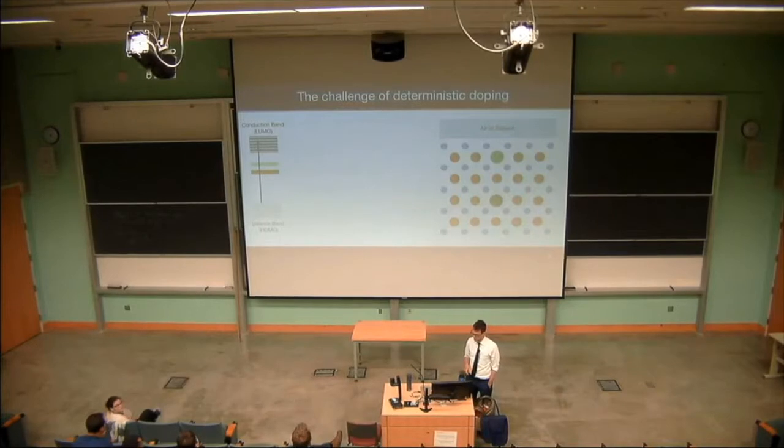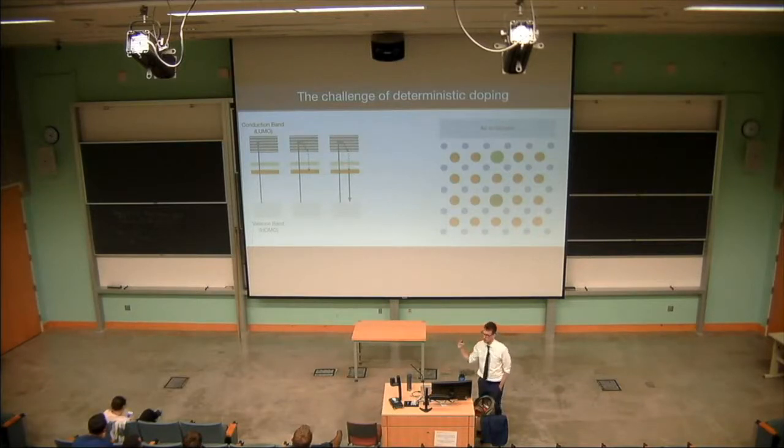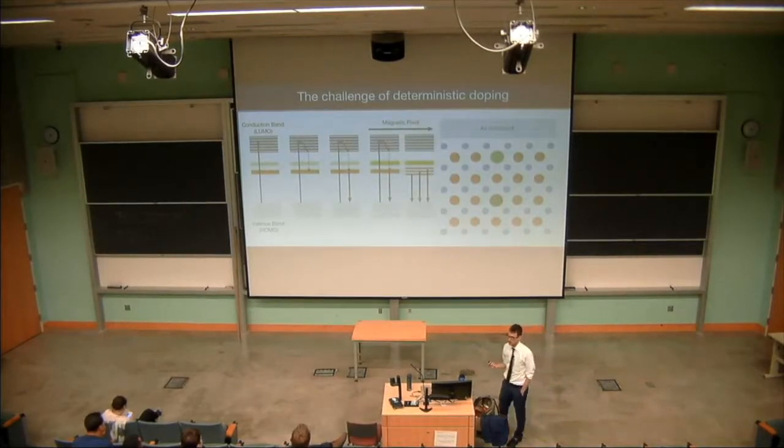This means that if you randomly introduce dopants into a solid-state lattice, you could end up with a distribution of energy levels. And now you could access different energy levels, or really you would always access typically the lowest energy level among these. And so you would perhaps only see some subset of dopants in the material that you're working with. If, for example, some of these states have different symmetries than others, these could also lead to different splittings in a magnetic field and different spin properties.